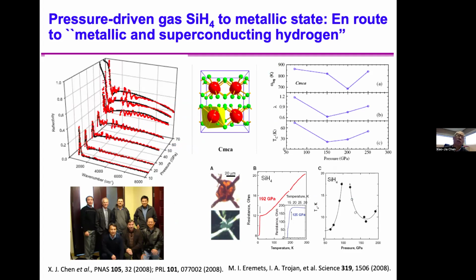We published a paper, the first experiment regarding silane. We reported the high pressure phase transformation, also the possible metallic state. Even though somebody argued this probably was dissociation or other kinds of issues. However, when we did a calculation, we could see the Tc at high pressure was not that high. At 150 GPa, there's a Tc around 20 Kelvin in this system. Actually, from Michael's work, published later that year in Science, they indeed reported a Tc around 17 Kelvin in that system at such pressure.